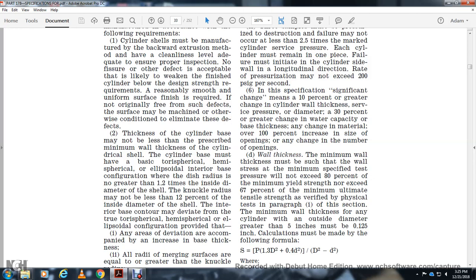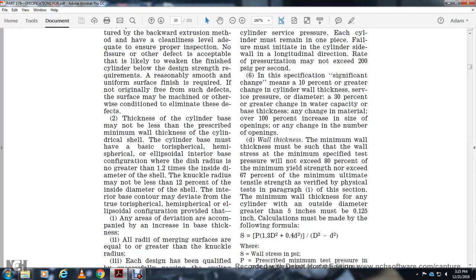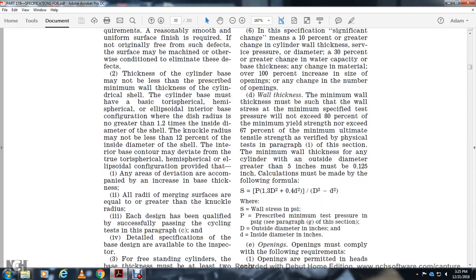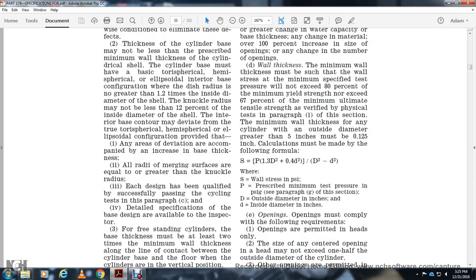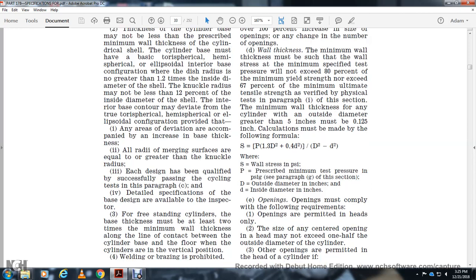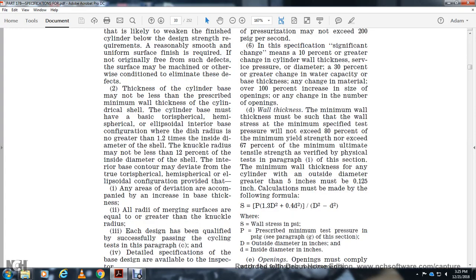Any area with deviation accomplished by increase of the base thickness, all radii meaning equal to or greater than the knuckle radius. Each of the designs must have been qualified successfully, passing cycling testing, with the detailed specification of the base design available for inspection. For a freestanding cylinder, the base thickness must be at least 2 times the wall thickness. Along the line of contact between the cylinder base and the floor, with the cylinder in the vertical position, welding and brazing is prohibited.